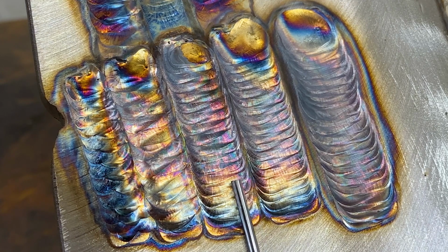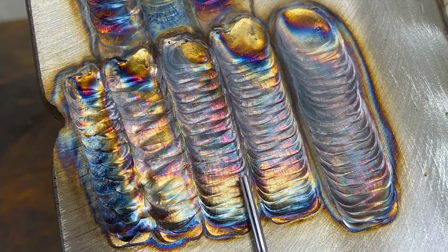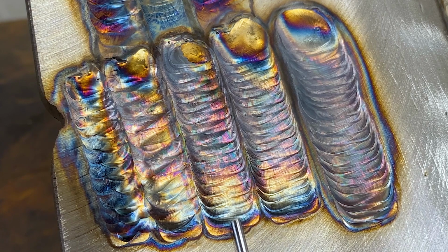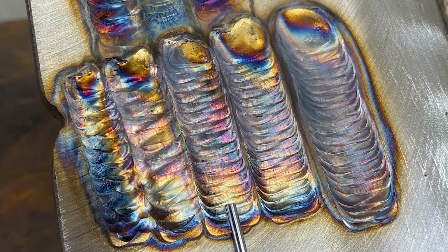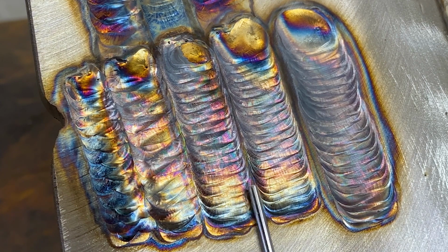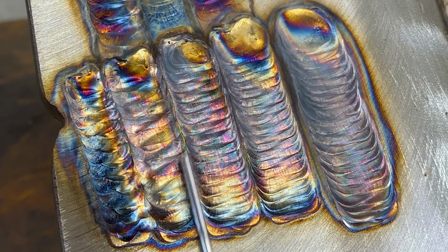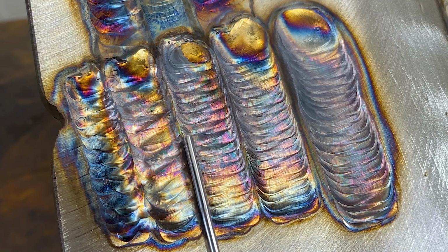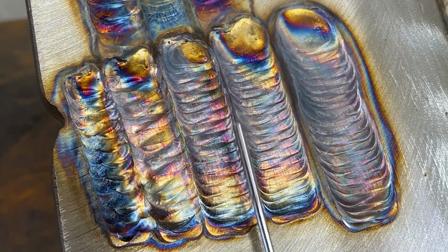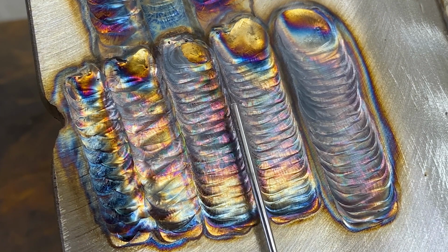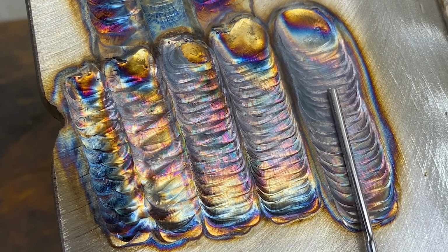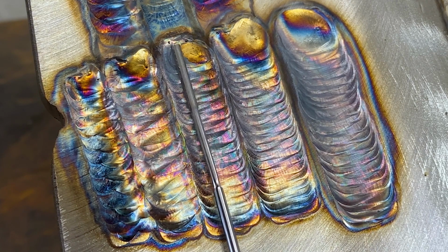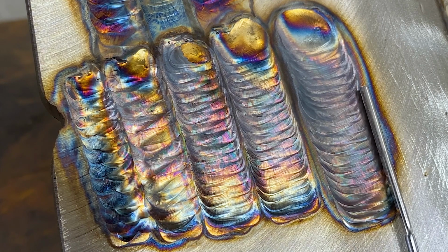Middle of the pack here is where I think is ideal for this situation based on my travel speed, my tungsten stick out, and my technique, along with my rate of filler. Okay? You could tell it was flowing. It was running the way it should. It looked free. It looked like I could manipulate it and do whatever I wanted to do with that weld, with the puddle at the time. It's uniform. Oxidation rate was very good before I continued to run out. But you can just tell out of the 5, it's the best weld.